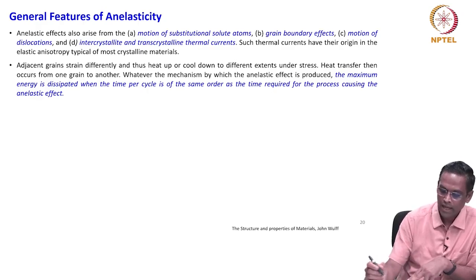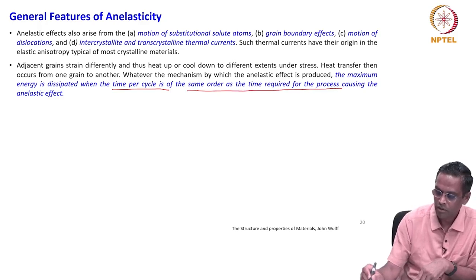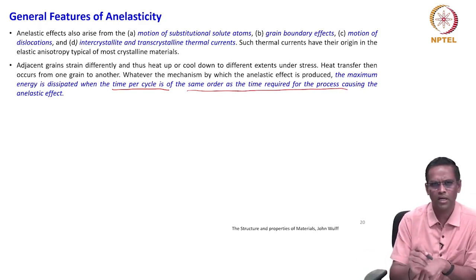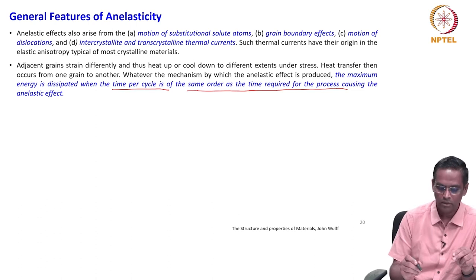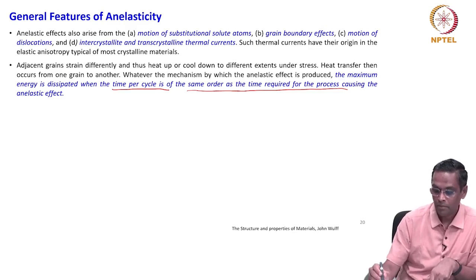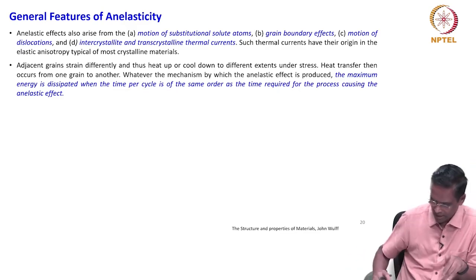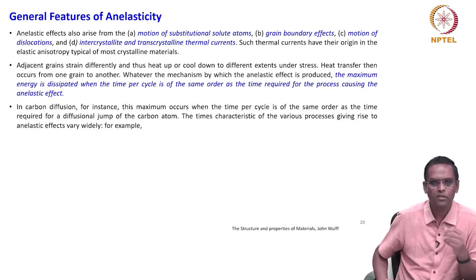Whatever the mechanism by which the anelastic effect is produced, the maximum energy is dissipated when the time per cycle is of the same order as the time required for the process causing the anelastic effect. Very important. It looks a little confusing, but when we look at a concept like relaxation time, this statement will become much more straightforward. The time per cycle should be of the same order as the time required for the process causing the anelastic effect. Very important ideas, you have to relate this to physical events, then it is interesting. Otherwise, it looks like